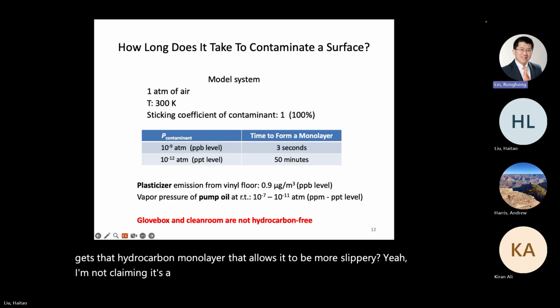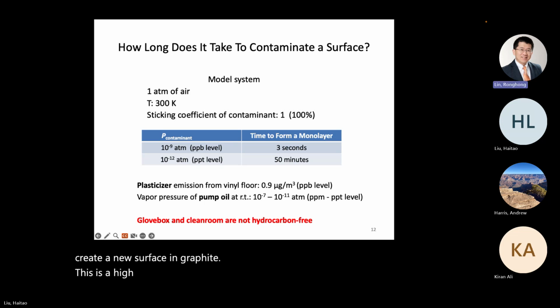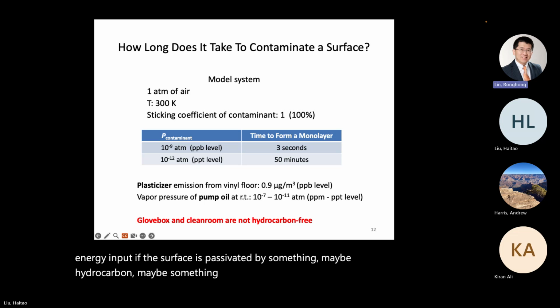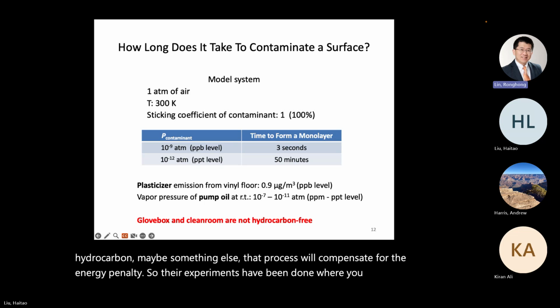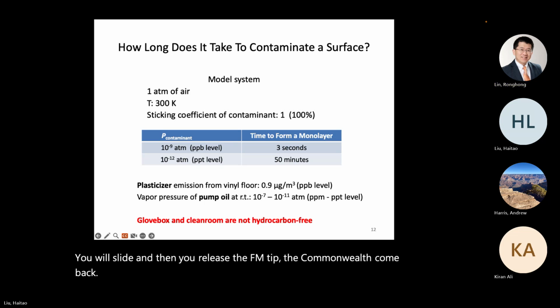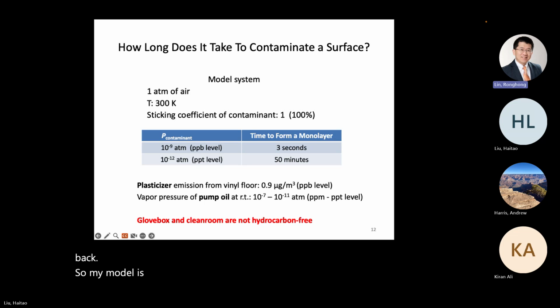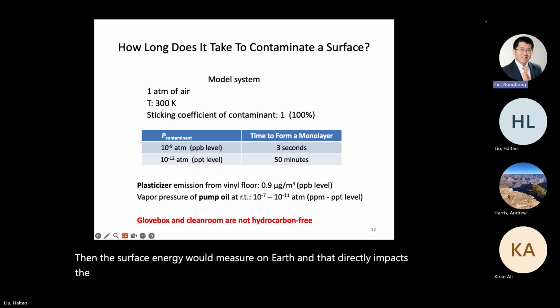Yeah, I'm not claiming it's a hydrocarbon, but the bottom line is when you create a new surface in graphite, this is a high energy process, right? You create a new surface, you need energy input. If the surface is passivated by something, maybe hydrocarbon, maybe something else, that process will compensate for the energy penalty. So there are experiments where you have a graphite column, use an AFM tip to push it in ultra vacuum. It will slide, and then you release the AFM tip, the column will come back. So my model is that in outer space, the apparent surface energy of graphite suddenly becomes higher than the surface energy you would measure on Earth, and that directly impacts the sliding. It's less likely to slide in an ultra vacuum environment.